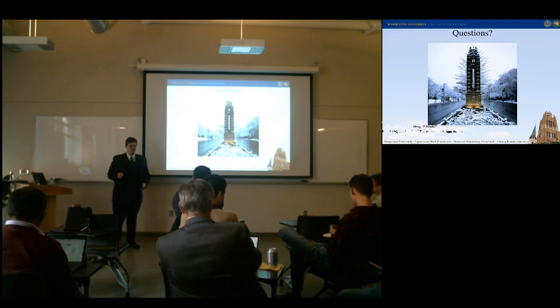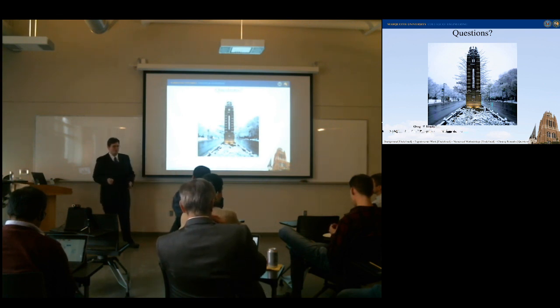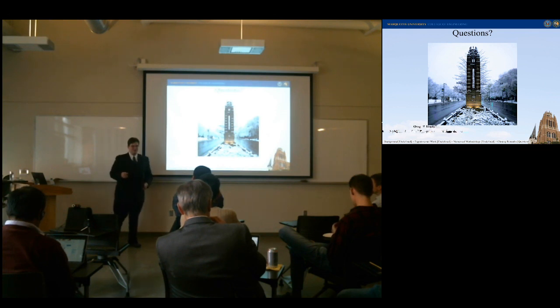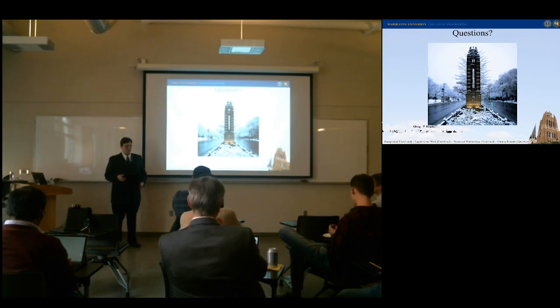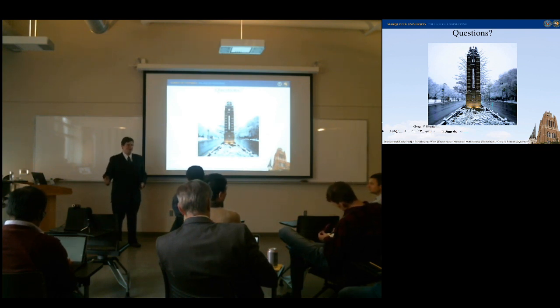But in sandstone, it's really interesting because you have those pores. Not only do you have all those mechanisms of strength that you would have in a crystalline material, you also get pressure hotspots because you have sharp corners, and so you'll have some regions which will liquefy immediately, and you'll have jetting inside of your sample, which is pretty interesting. So you have to include those inside of your strength models and in your simulations if you want to capture the full failure of sandstone as a mesomaterial rather than just a single crystalline grain.